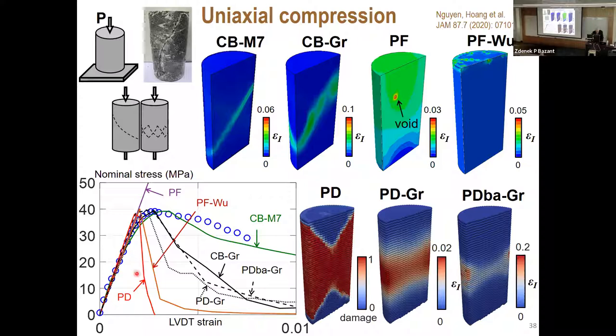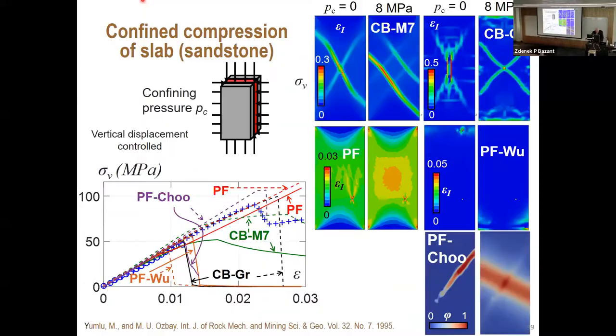Peridynamics drops steeply down, which is incorrect. So this is all poor, also the patterns. Another test, and that was not only for concrete, but for sandstone. A slab which is confined at zero transverse strain, rigidly placed slabs, is loaded by controlled displacement vertically and is under different confining pressures from the side.